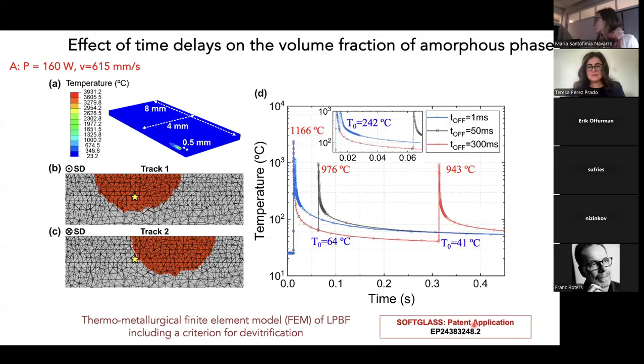But then Professor Adrián Bocardo carried out some simulations for us to allow us to further understand what was going on. So he used this thermometallurgical finite element modeling. Also, he modeled two passes. And here are the two passes. This first graph here is a cross-section of the first track. And then below here, we have a cross-section of track 2. And this yellow star is the control point. Here is where the model allowed us to track the temperature evolution. So this is what we are showing here in this graph to the right. And we did that for the 3 time delays that we are investigating. So the default value, 50 milliseconds in black and 300 milliseconds in red.